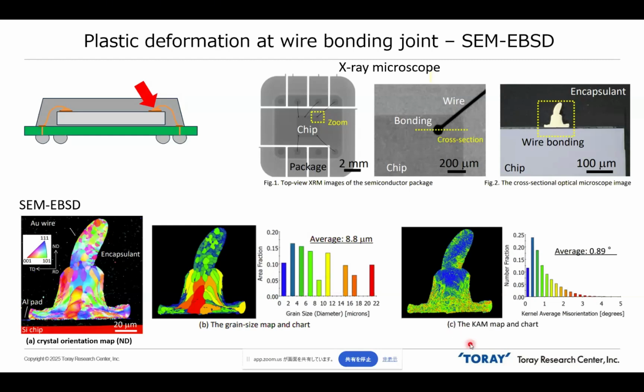On the other hand, let's see the KAM map on the right side of this slide. The KAM map shows the crystal orientation difference with the surrounding pixels in this experimental data. Generally speaking, a large KAM value means plastic deformation. In this sample, the base of the wire bonding has a greater KAM value. So the base of the wire bonding should be tightly connected to the IC chip, thanks to the plastic deformation. So EBSD is a very useful technique to get information about material strengths through the crystal grain size and orientations.